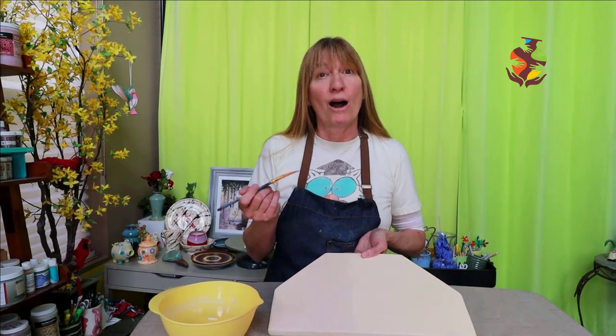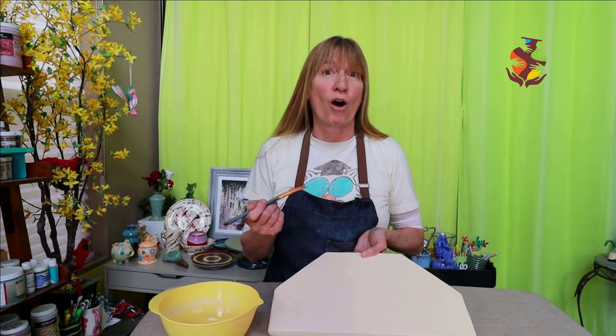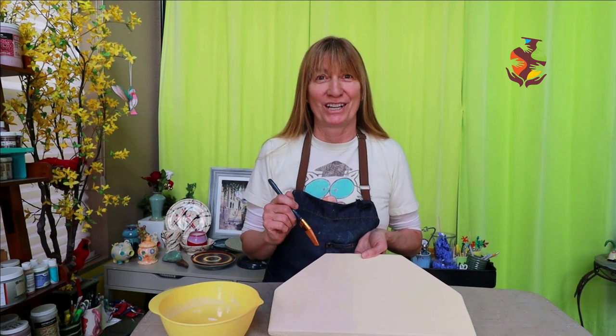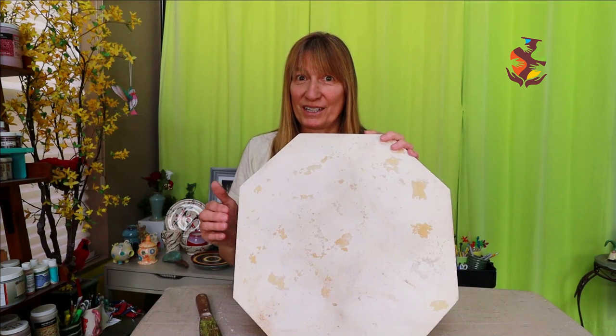When you do drip glaze or see kiln wash start to flake, you need to reapply. Scrape off any glaze drippings or flaking of the kiln wash and always wear eye protection and a dust mask when doing this. Then reapply the kiln wash by dabbing some on the bare spots. Depending on how hot you fire the kiln and how often you fire will determine how often you need to reapply the kiln wash. There is a downside to kiln wash.